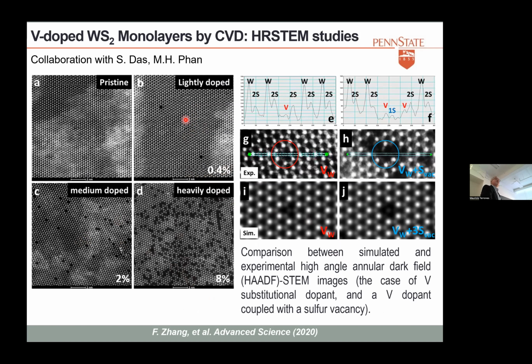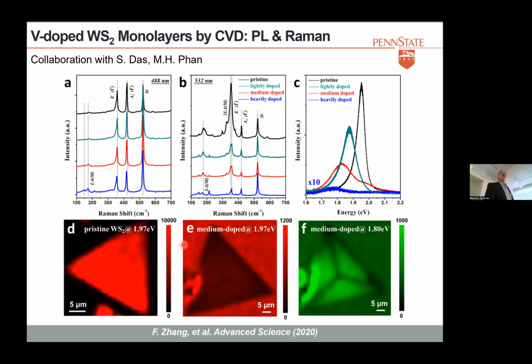I selected these because they are representative. One thing, these are not vacancies, these are vanadium atoms, but they are lighter, so very light Z contrast. And one thing that I want to show you is that in the medium doped case, the average distance between the vanadium atoms is around 1 to 2 nanometers. When it's 8%, basically you have clusters of vanadium and they're very close to each other. So I just want you to remember that, because that might change the properties of the systems that we're seeing. But with this method, we can put different concentrations, and we can start studying the systems.